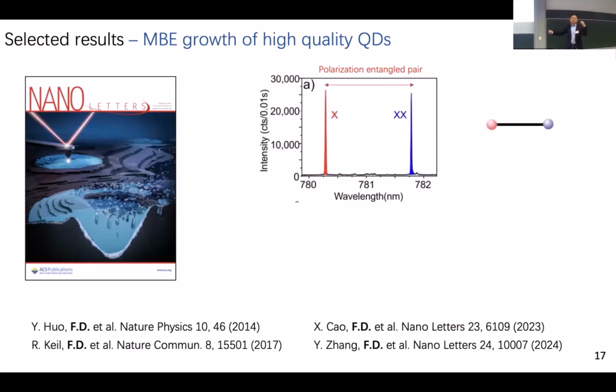We can use a laser to interrogate the system. This is the spectrum. First of all, we adjust the amount of the filling material in order to shift the emission to 780 nanometer. Why? Because 780 nanometer is the absorption line of rubidium. So the idea is that we can put one of the photons into the rubidium, so the rubidium acts like a memory, and after some time we can take the information out. Not the same photon, of course. These emission lines have almost identical intensity, so they are pretty bright. With an integration time of 0.01 second, we still have around 30,000 counts in this short period. These two emissions are entangled in their polarization, okay?